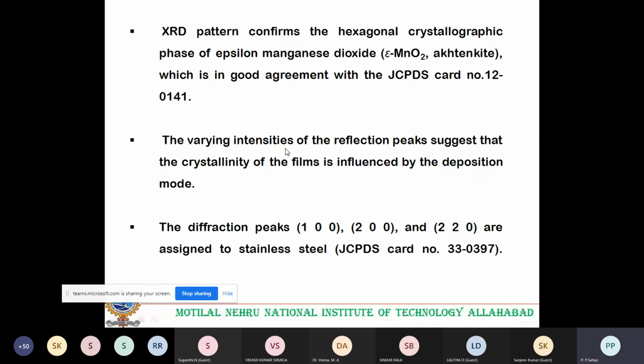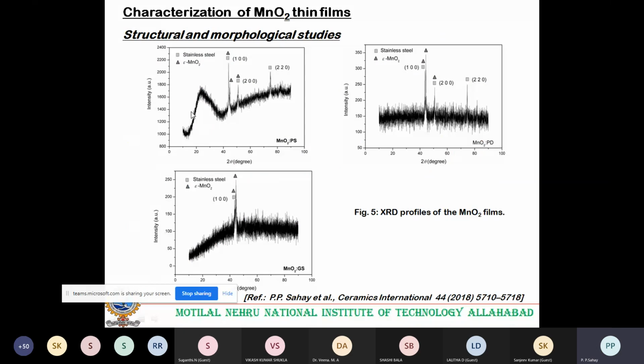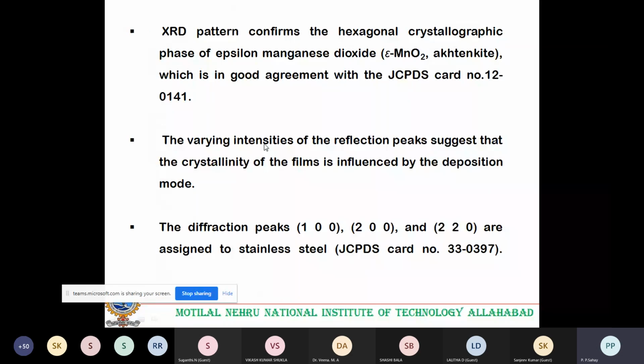Now look after this one, there the intensity is varying. The XRD peak intensity is varying. Variation in the intensity means variation in the crystallinity of the film. When it is high, crystallinity is better. When it is low, crystallinity is poorer. So the varying intensity of the reflection peaks suggests that the crystallinity of the films is influenced by the deposition mode, because intensity was different for the different films, which were deposited by different deposition modes. Diffraction peak 100 corresponds to the stainless steel peak.